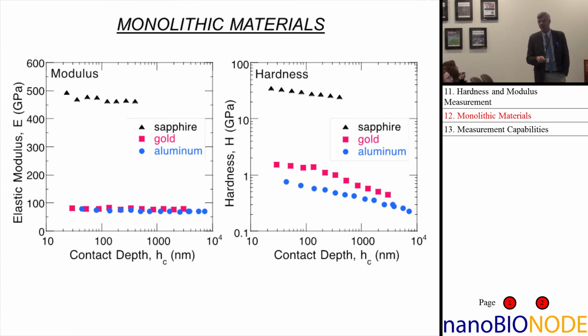But here's the hardness over here. Now notice that this is a linear scale over here, and this is now a log scale over here. We're putting it on a log scale so we can get everything plotted nicely on one plot. But notice that even on the log scale, you're seeing the hardness creeping up. As you go to smaller depths, the material appears to be harder. As you go into gold, same thing. And even a little bit in sapphire. As you go to smaller and smaller depths, the hardness is going up and up,